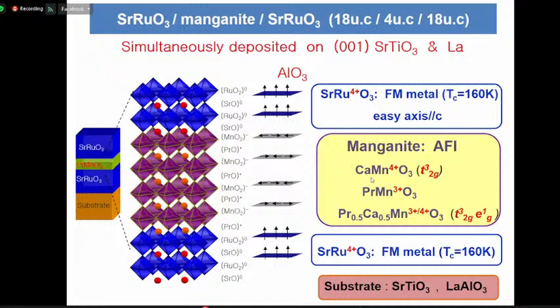We use these three kinds of manganite. All of them are antiferromagnets and insulators, but they have different valence states: 4 plus, 3 plus, and half and half, like this. Also, we change the substrate like this. We use two substrates. Strontium titanium oxide has a larger lattice parameter than lanthanum aluminum oxide.